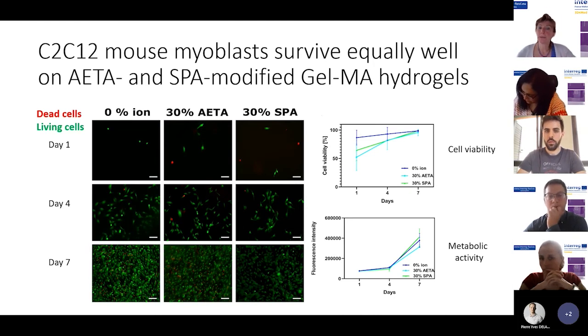So this was quantified as well. And here you can see the cell viability on the different days. And you can see that there is no difference in the viability of the cells in the three conditions. And then we also looked at the metabolic activity. This means that the metabolites that they produce are measured in order to see whether the cells are metabolically active, which means that they are growing and dividing, and that in fact they are healthy. And also here we could see that indeed there was more and more metabolic activity because there were more and more cells, and there was also no difference between the different hydrogels.